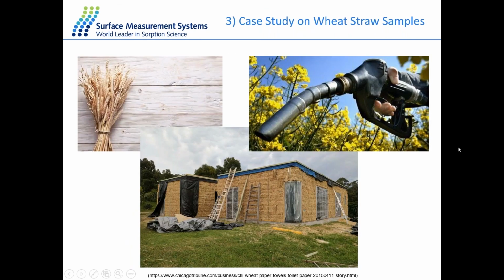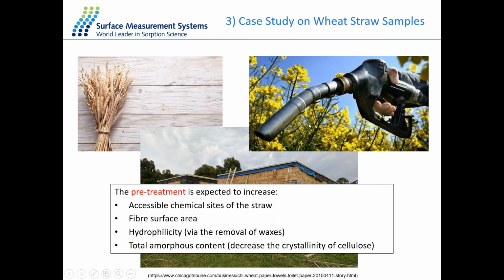The next application is about the wheat straw sample. So straw sample can be used as some kind of construction material in the building industry, or we can also produce biofuel from the wheat straw sample to replace fossil fuel. And one of the crucial steps of producing the biofuel is the pretreatment of the straw sample to increase the accessible chemical sites on the straw. For example, to increase the surface area, the hydrophilicity of the material, and also the amorphous content inside the material. So with the DVS technique, we can characterize different treatments of the straw sample to study the BET surface area as well as the water sorption kinetics.